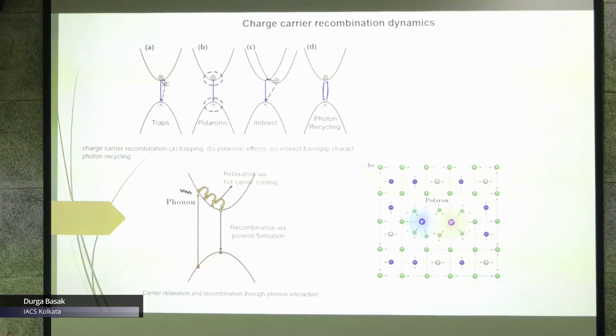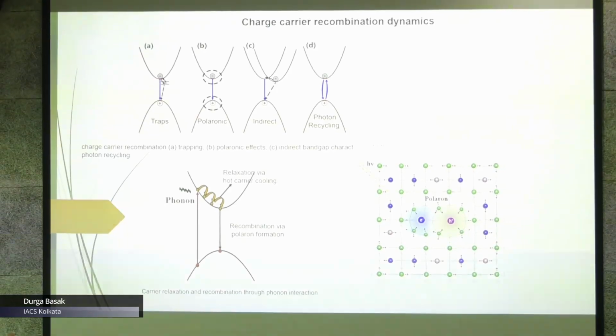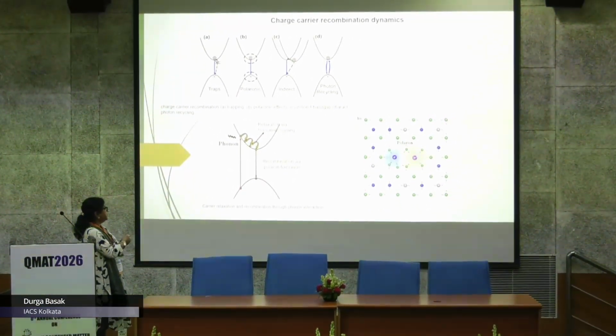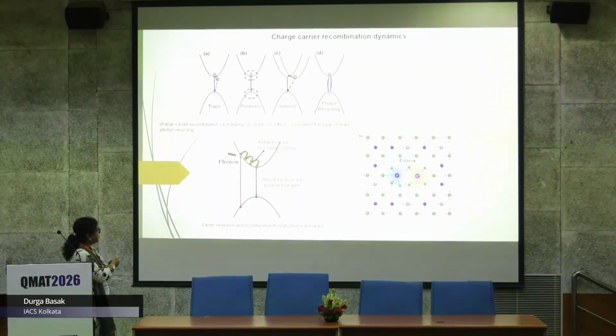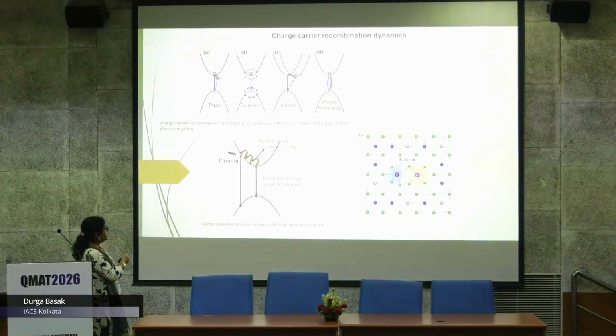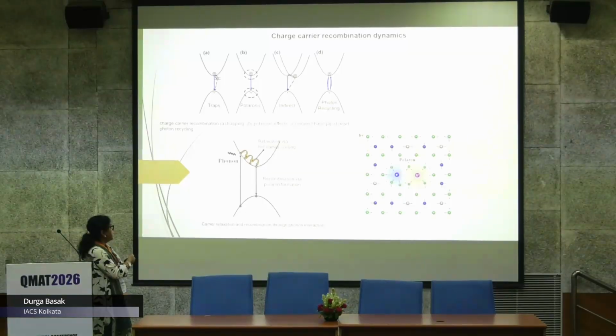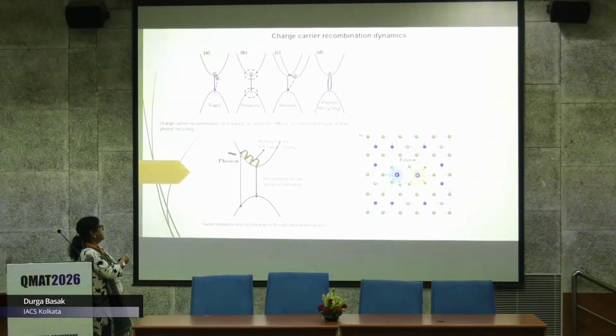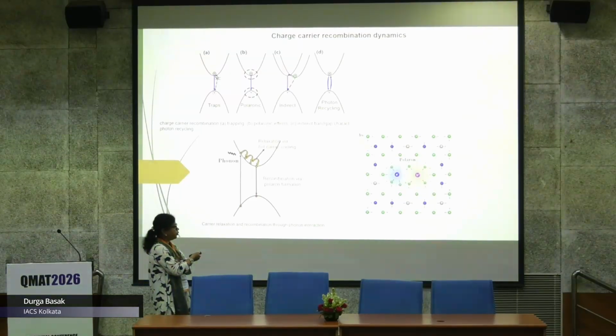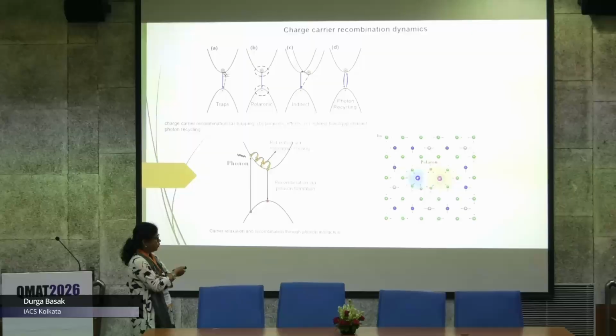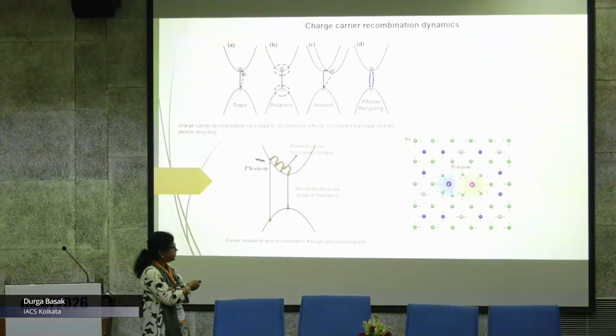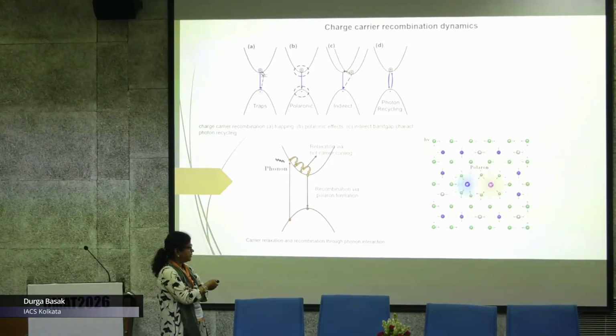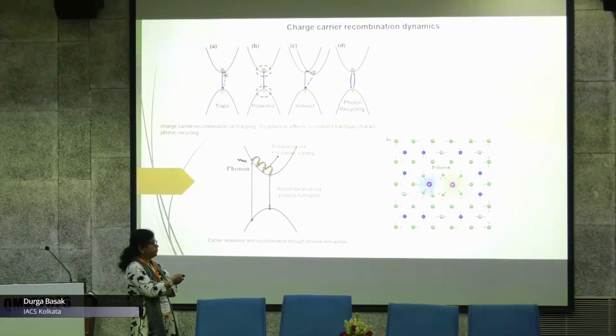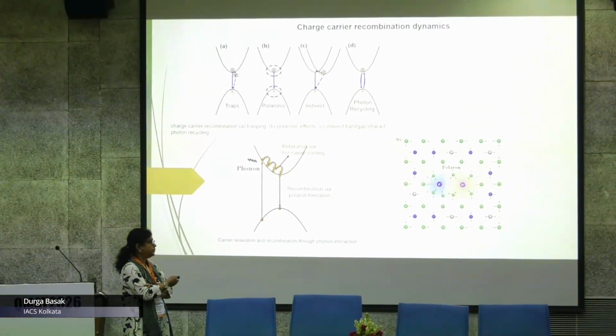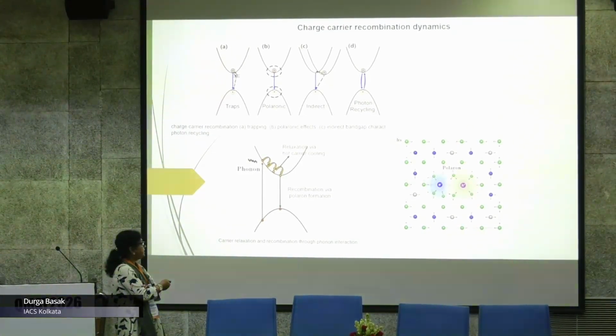So to explain more about this polaronic effect in recombination, when light falls on a material, it is absorbed by that material and an exciton is generated, and the exciton is separated into electron and hole polarons, and then these electrons and holes dissipate thermal energy to the local phonons, and then finally they equilibrate by transmitting the energy to the lattice, and the hot carrier becomes cool. This effect is schematically shown here, where electron polarons and hole polarons are formed. And this formation of polarons is sometimes very beneficial because they are screened from the Coulombic attractions, and many outstanding electron transport properties or electron extraction happen because of this electron polaron formation.